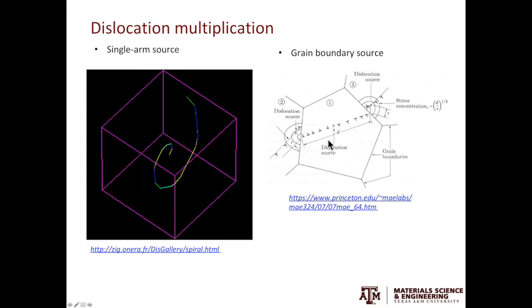Assume you have a dislocation source within the grain and dislocations are emitted from this dislocation source. Dislocations will be blocked by the grain boundary and create a stress field in the neighboring grain. The stress field will lower the energy barrier for dislocation multiplication from this part of the grain boundary, making grain boundaries effective sources for dislocations. In fact, the last example I give you will be a preview for what we are going to discuss in the next video: how dislocations can arrange themselves and form boundaries.